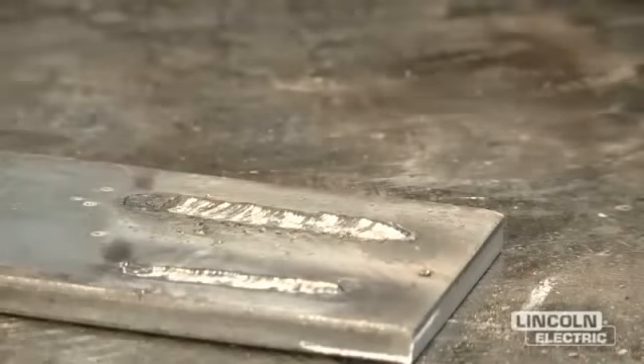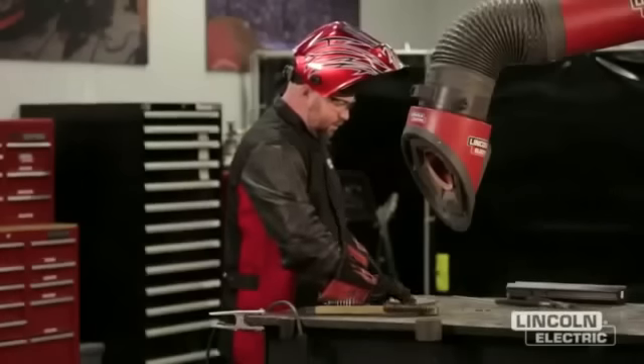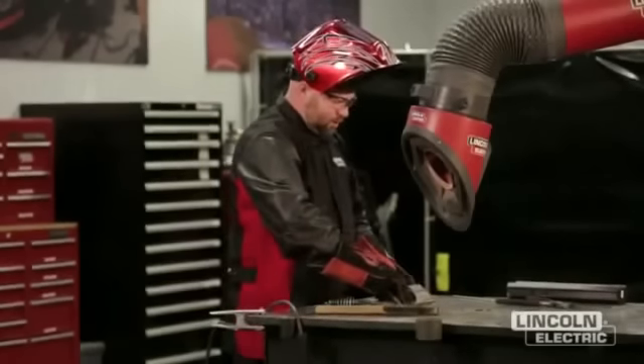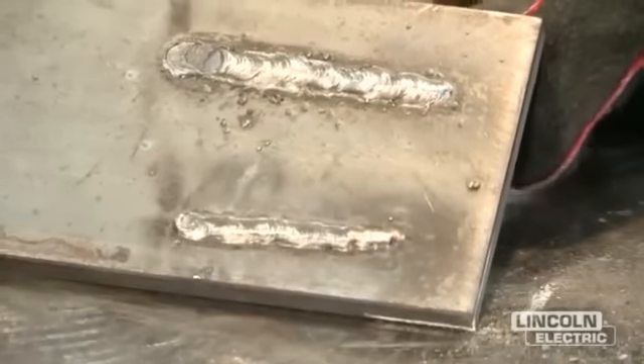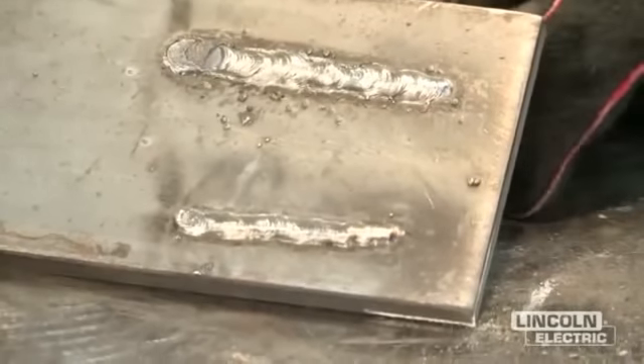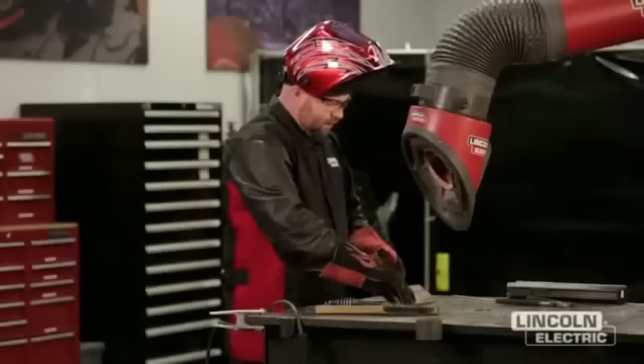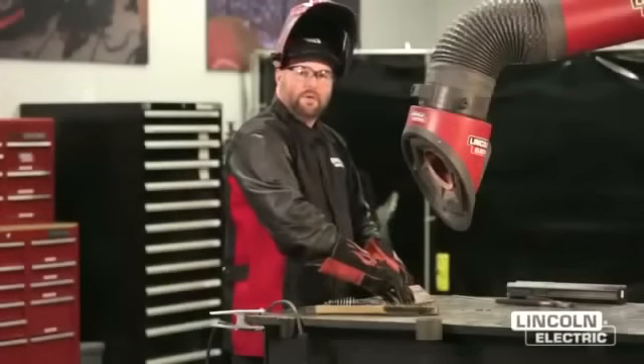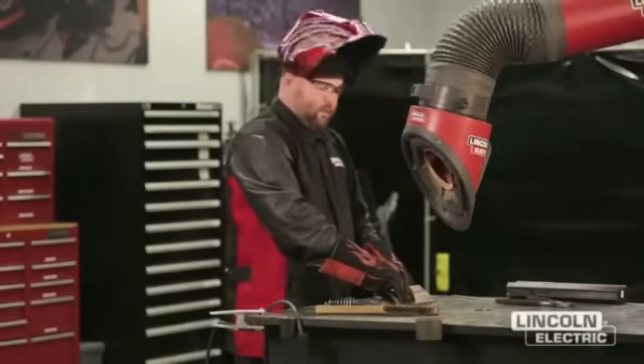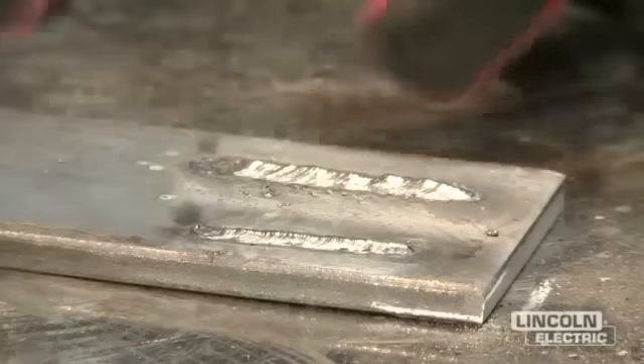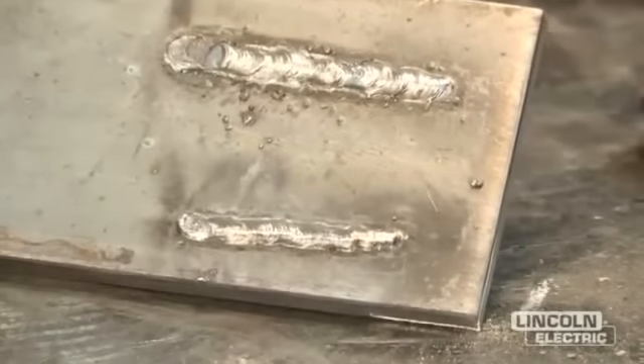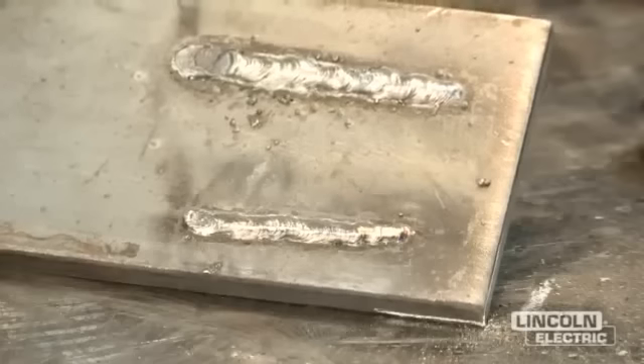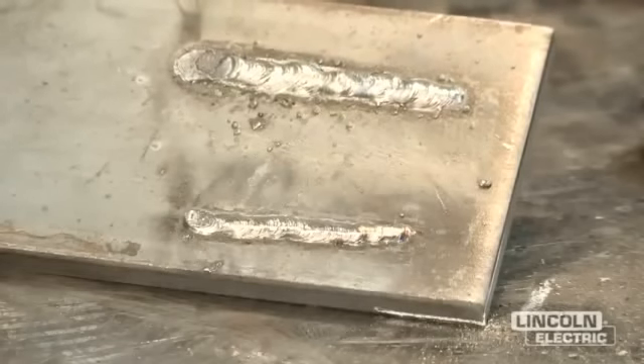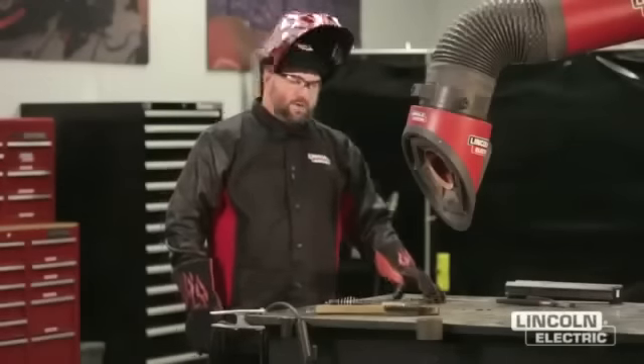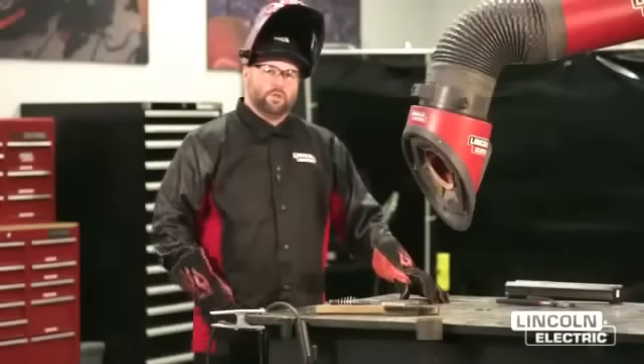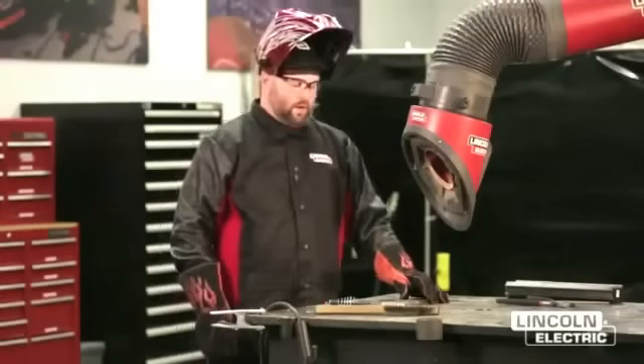Okay, so now we made a weld at 150 amps, and if you look, we can compare the two welds. The bottom one is at 90, and the top one was at the high end of the range of 150 amps. So ideally, we would probably be right about in the middle somewhere, maybe 125, and we would get it right. So you'll notice a little bit of extra additional spatter as well, and the weld is a little bit wider. Now, we've looked at too low a current, too high a current for our troubleshooting of our welds.